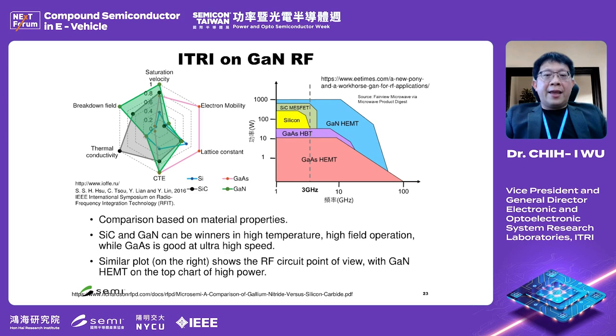If you look at the right-hand side here, gallium arsenide can deliver very high frequency, but because of its smaller band gap, the material is not good for delivering power. Silicon carbide is good for power devices, but the frequency is quite low, so it's not good for high frequency applications. So for the power amplifier for 5G and beyond 5G applications, which need both power and high frequency, gallium nitride is probably the best candidate, and that's what ITRI is working on.